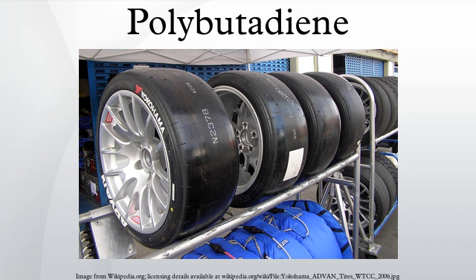About 25% of produced polybutadiene is used to improve the mechanical properties of plastics, in particular high-impact polystyrene and to a lesser extent acrylonitrile-butadiene styrene. The addition of between 4 and 12% polybutadiene to polystyrene transforms it from a fragile and delicate material to a ductile and resistant one. The quality of the process is more important in plastics use than in tires, especially regarding color and gel content. In addition, the products need to meet health requirements due to use in the food industry.